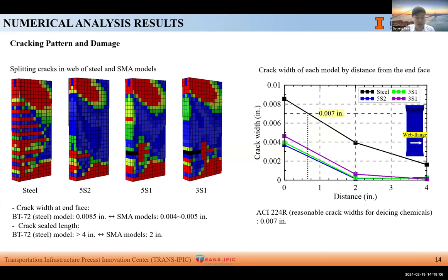However, with replacing SMAs, the crack width reduced to below 0.005 inches at the surface, and after passing SMA stirrup at a distance of 2 inches, it was nearly sealed. With analyzing cracked area and crack width, we could find that applying SMA in pre-tension girder could prevent extensive cracking and improve serviceability.